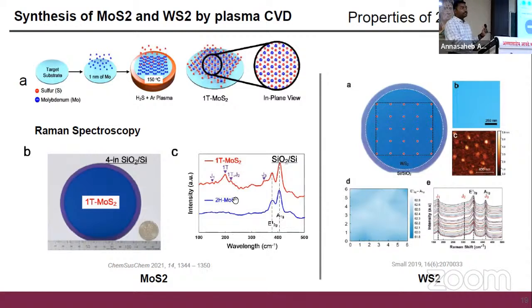After the synthesis, first we use Raman spectroscopy. As you may have learned about Raman spectroscopy, we use that technique to first confirm the formation of these sulfides. Typically MoS2 and WS2 show the E1(2g) and A1g peaks. Depending on the peak formation, we can also separate the 1T phase from the 2H phase, since additional J1, J2, and J3 peaks will be present in the 1T phase. Similarly, the Raman technique can also be used to confirm the uniformity of the synthesis process. Even if you use another technique to synthesize, you can use the Raman method to confirm whether the whole area is synthesized or not, which we'll talk about further.